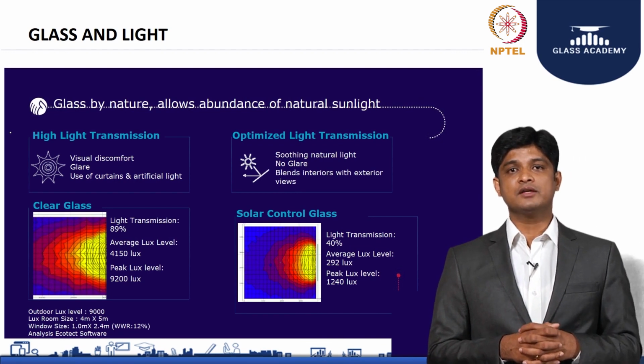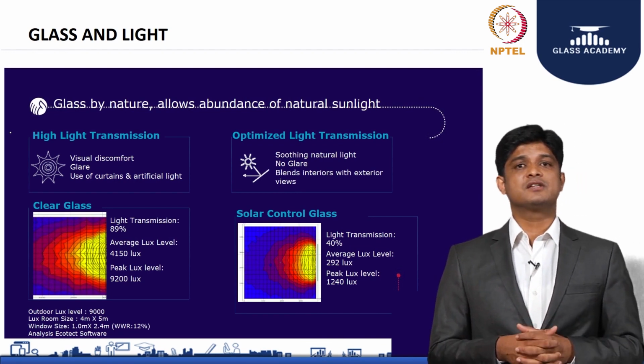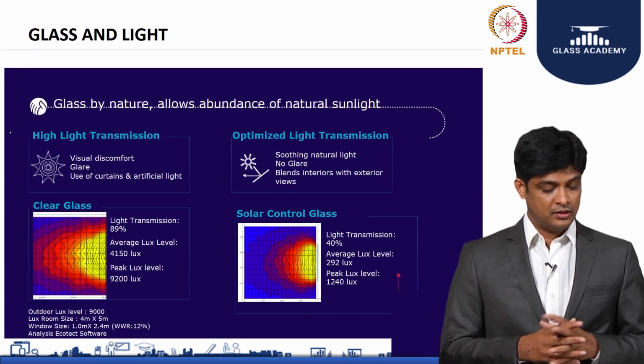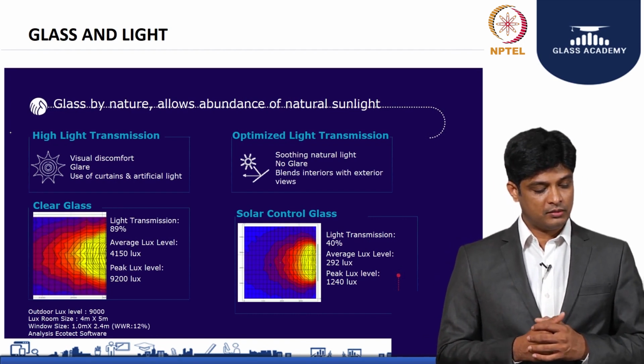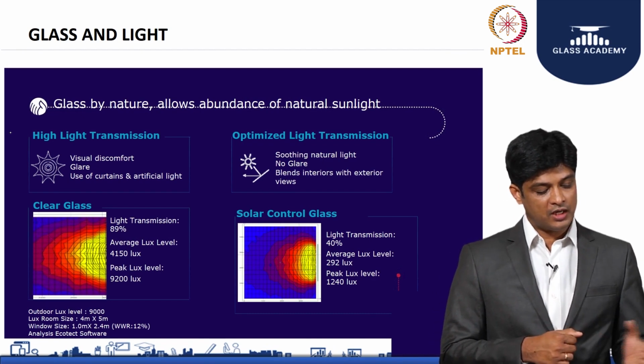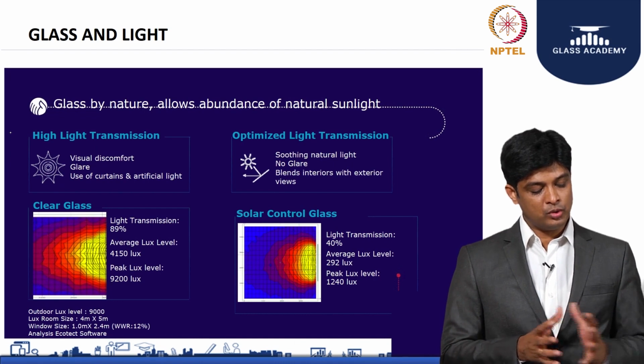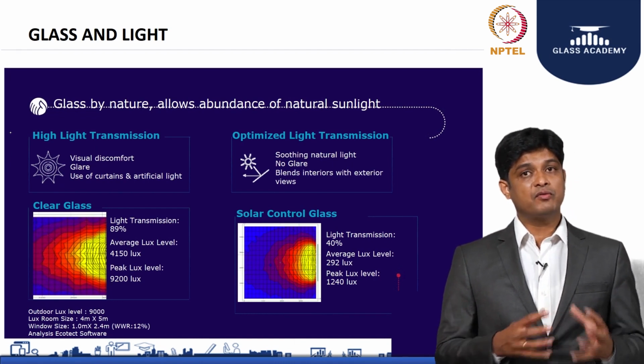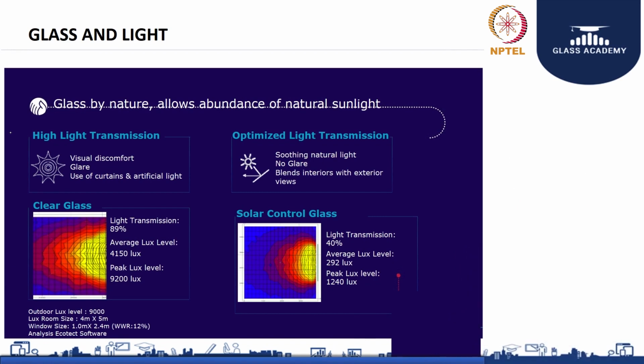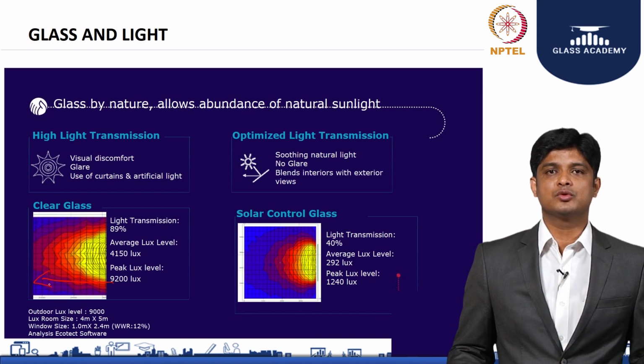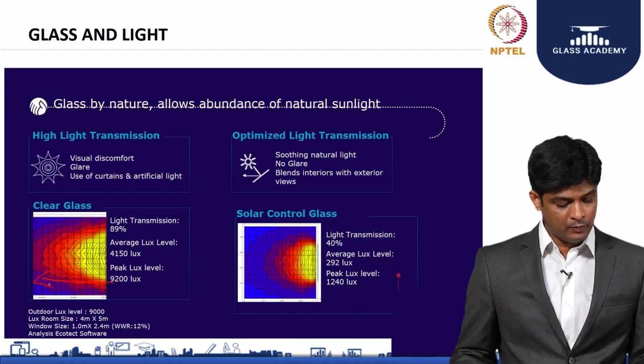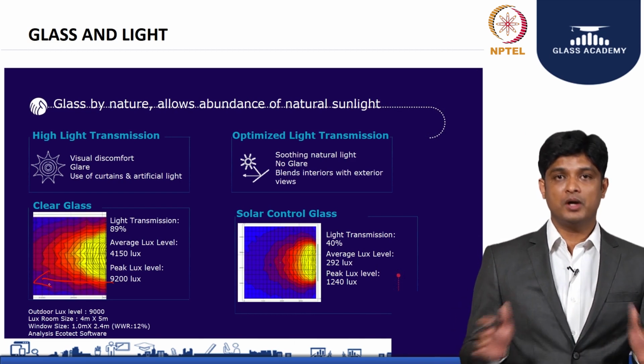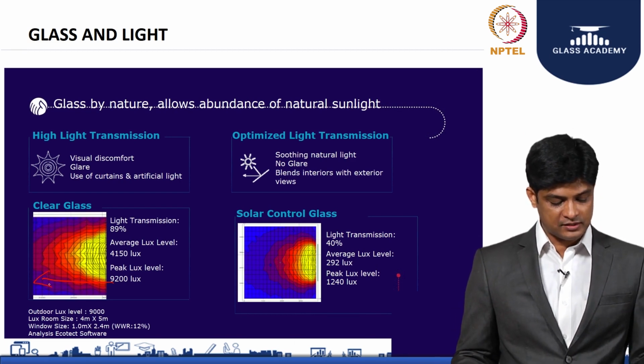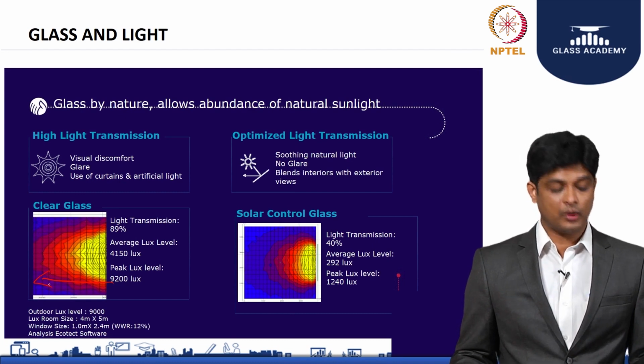So what is a traditional mistake we make? We have a clear float glass, 6 mm or even 5 mm thick, which has a light transmission of about 89%. If you see here, the problem can be understood very clearly: based on the color code, the more yellowish means the lux level, which is above 4000, is more in that zone. It indicates that when the light transmission happens, the depth of light penetration is restricted to as much as 1 to 1.5 times the height of the window. So that entire zone accumulates the amount of light coming in. That's why the average light lux level is very high and even the peak goes up to 9200.